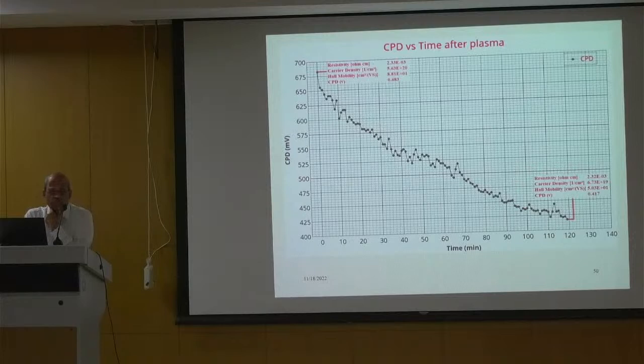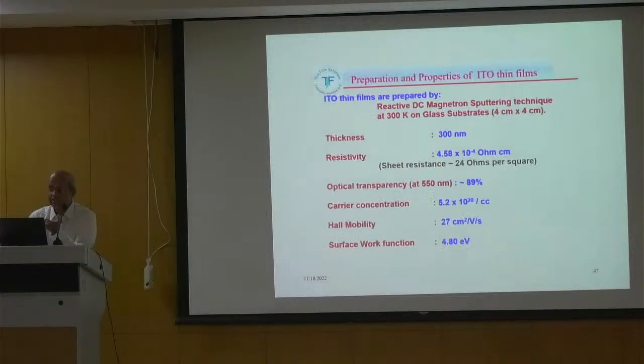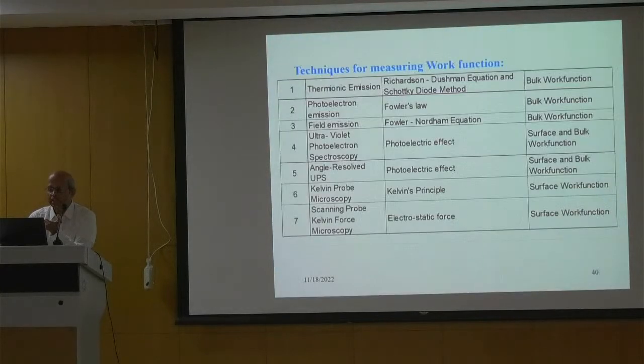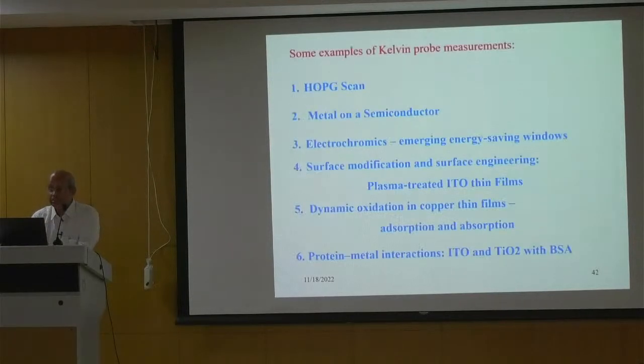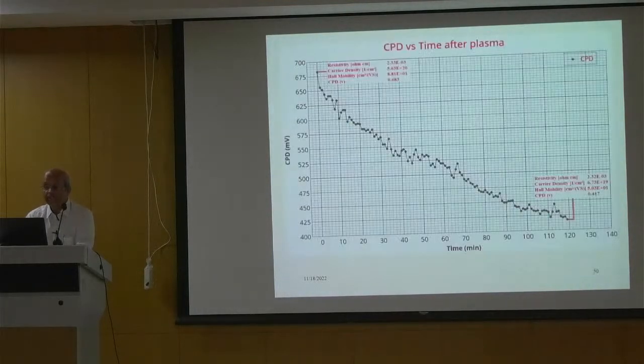If you want to measure the work function, you have seen there are about 7 techniques. Say, for example, angle resolved UPS. You have to take the sample, put it in the machine, start evacuating it, then conduct the experiment with a UPS probe. It takes a lot of time. By that time, the surface has already modified. For example, if you take about 20 minutes to do the entire experiment, the CPD has already come to 580 millivolts. Means the surface starts relaxing, and once the surface starts relaxing, you can't really measure. So the question is, how much relaxation is the surface having? Can you follow the dynamic changes of the surface as far as the electrical signature of the surface is concerned?